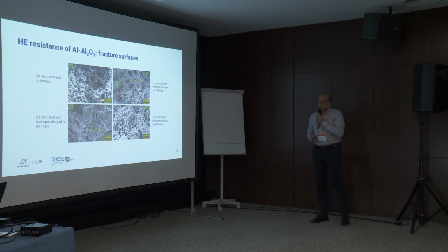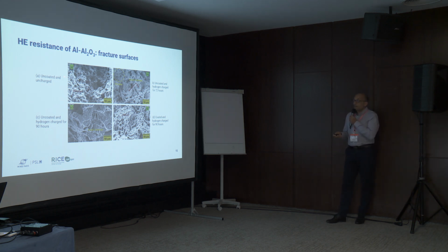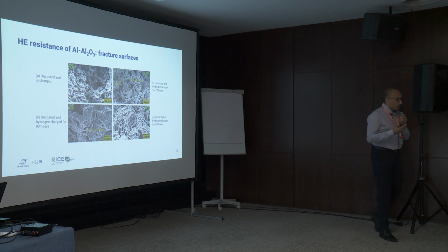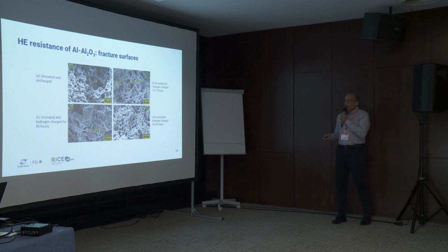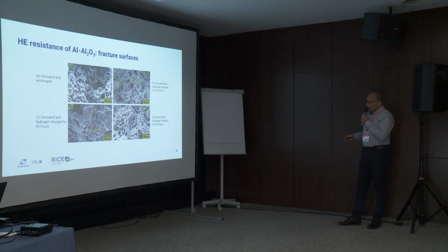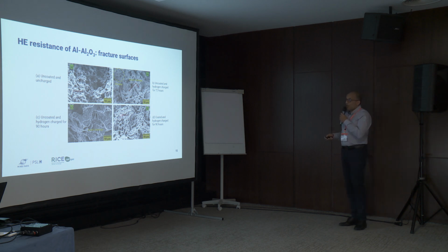To conclude, we also observed the fracture surfaces. Here you can see the uncoated and uncharged specimen, a typical ductile failure with dimples. Here you can see the effect of the hydrogen, with a mixed rupture mechanism with dimples and quasi-cleavage. When you increase the charging time of the specimen, you can see fewer dimples and more quasi-cleavage. And here, when you put the coating, you see that there's no effect on the rupture, and we regain a ductile fracture like the as-received material.